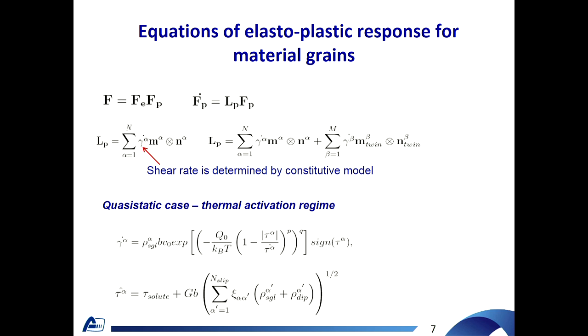In this method deformation gradient decompose to factors elastic and plastic. Plastic deformation rate is expressed in this form. Then in LP we can use different terms for different plasticity mechanism. The dislocation and twinning terms are shown here.